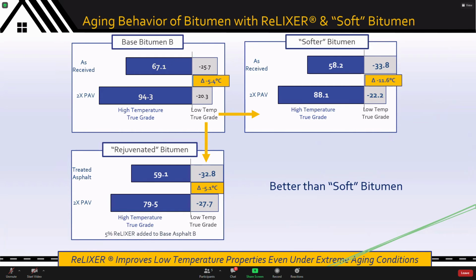As I mentioned earlier, this is delta TC data. Delta TC is a measure of the difference between the stiffness and the compliance in a BBR. Here is base bitumen that is aged. This is the delta TC number after aging, after PAV aging. This is for the base bitumen. This is the delta TC number for 1 grade softer bitumen obtained from the same refinery. A lower delta TC number is poorer than a higher delta TC number. And here is the delta TC number of this base bitumen rejuvenated with ReLIXER and then subject to 2x PAV, 40-hour PAV aging. And you can see that it is able to preserve the aging properties of the bitumen much better than softer bitumens.